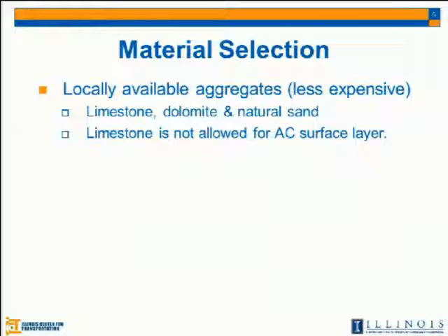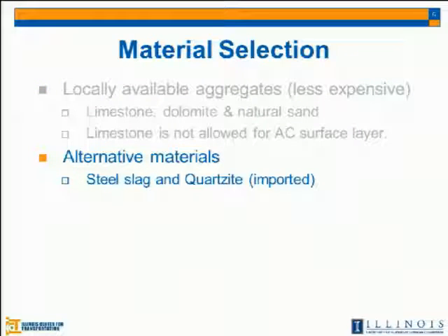But to save money on material cost, we try to use dolomite and natural sand as much as possible, but also try to minimize the use of natural sand. Some of the mixtures use steel slag, which is a byproduct of steel. It's relatively cheap, but this steel slag is very strong and has a rough surface. And we also use quartzite, which we imported from other states.